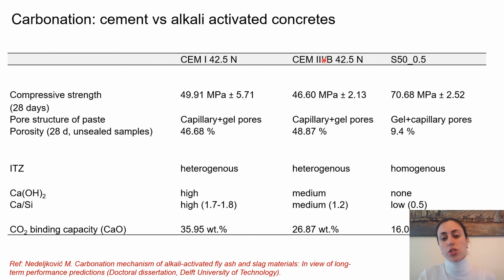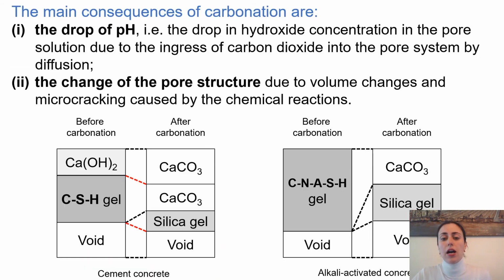So that means that for carbonation, it takes longer to carbonate the available calcium oxide, while for alkali activated materials, since they have a low calcium oxide content, consequently the CO2 binding capacity is lower, and then carbonation can propagate faster. So more details about this you can find in my PhD thesis.